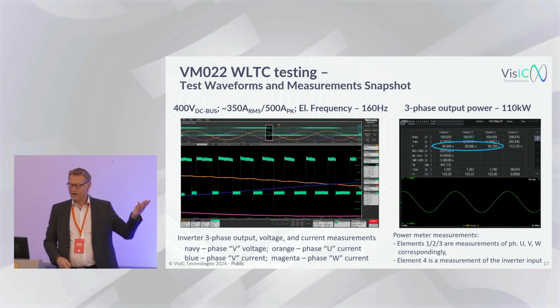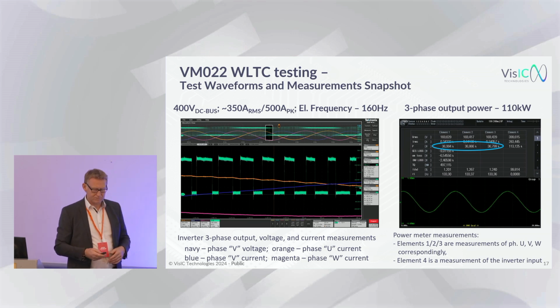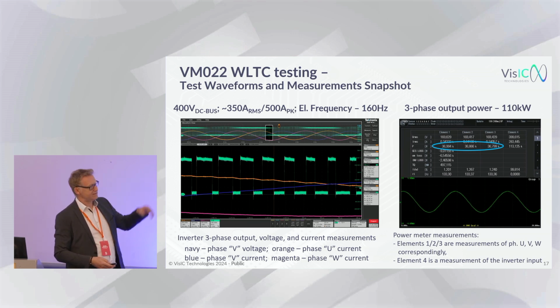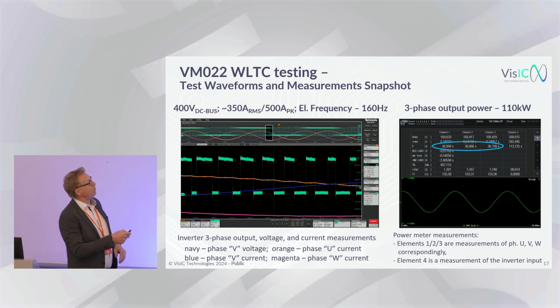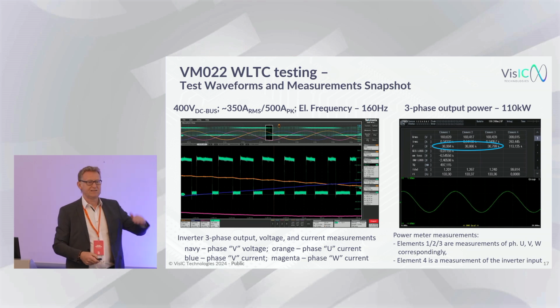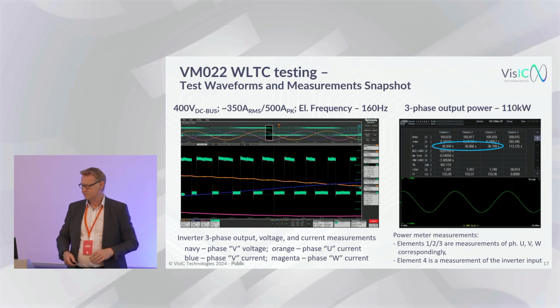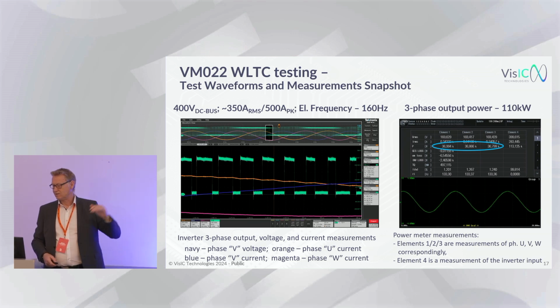Then we went even higher with the test. So this was the first testing. Then we did the second testing, and we extended the range up to 350 amps, going with 110 kilowatts.